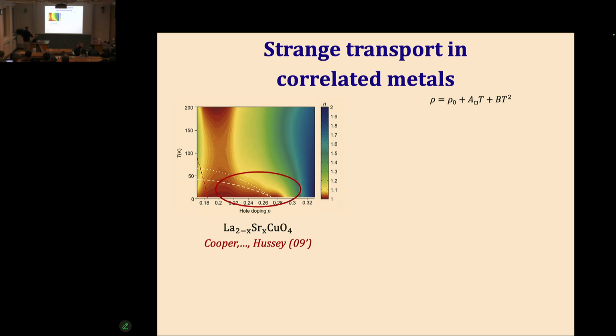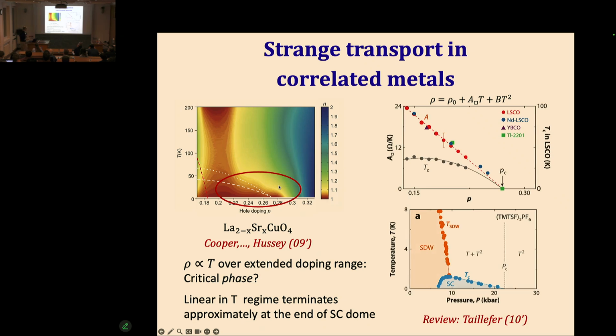All right, and let me also mention that this type of behavior of linear T resistivity that gets revealed when you suppress an unconventional superconductor is actually not special to the cuprates. That's actually seen in other materials. This is a compilation of data from different cuprates. What's plotted here is the coefficient of the linear T resistivity as a function of doping, and Tc as a function of doping for different materials. In this review article by Louis Taillefer, you see that there seems to be a correlation between where this A coefficient vanishes and where Tc vanishes.